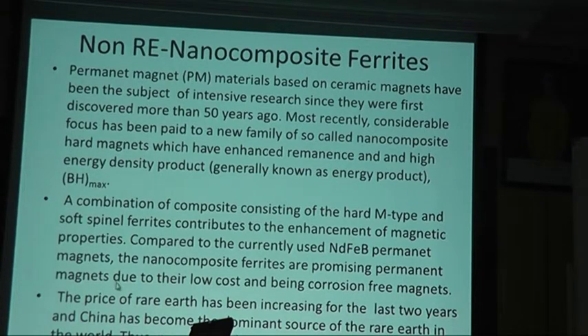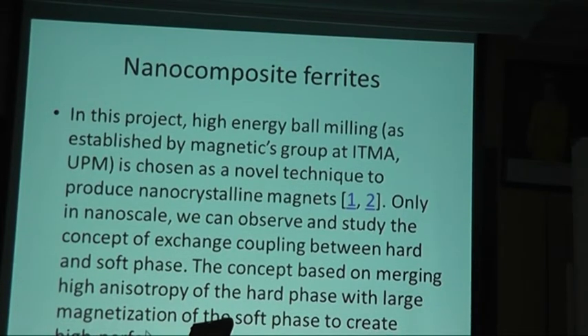In this project I'm going to use high energy ball milling, which is already established in ITMA. Hopefully by using this method I can produce nanoscale, because only in nanoscale can we get exchange coupling. But I found a few papers where, even though the grains are not less than 50 nanometer, they still can get exchange coupling. They still can enhance the remanence and energy product. You can see after this.